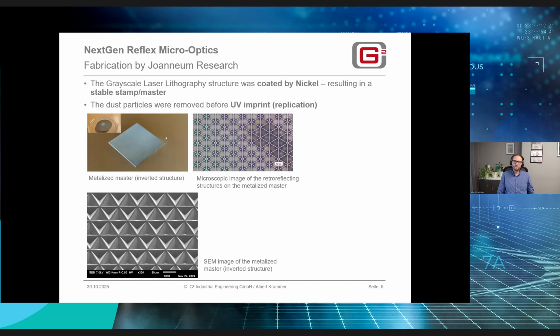Yeah, the next step to come to a functional prototype was then to produce a durable master, and this was done by coating this laser lithography structure with a nickel coating. This results in a stable master we could use for the replication. That is the most important part, to get some physical parts and prototypes to do some light lab measurements as well. What you can see here on the left top picture is the metallized master. Just for your information, this is 1 square centimeter, so we are talking about 10 millimeters by 10 millimeters with the pyramid height of 30 micrometers, just for remembering that.